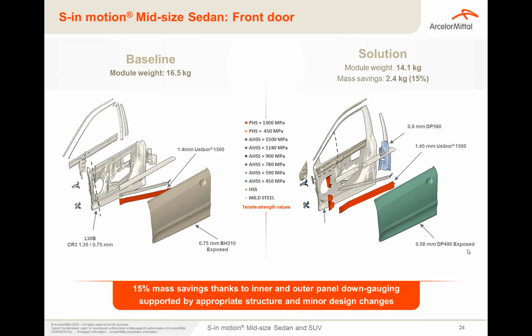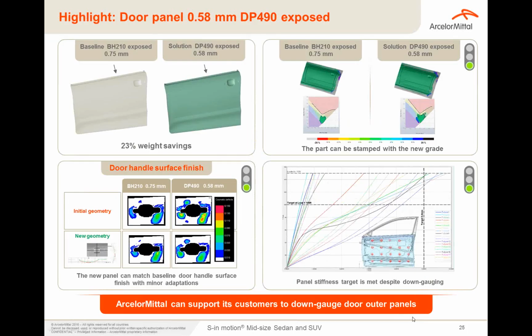We also applied our new grade for exposed panels, the Dual Phase 490. This grade has a very high dent resistance behavior and allows us to down gauge this panel, in that case, to 0.58 millimeter, compared to a baseline in bake hardening 210 grade at 0.75 millimeter, allowing 23% weight saving.